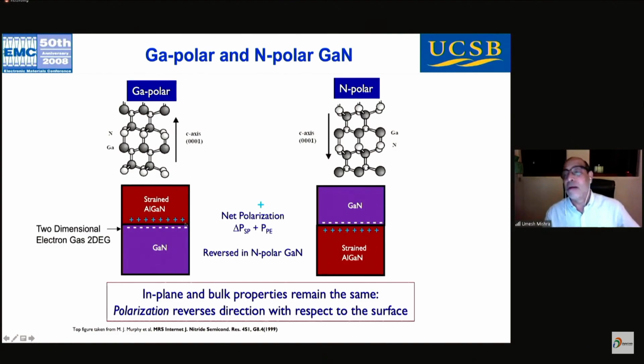When we say gallium nitride, at least folks talking about lateral gallium nitride devices, you basically grow aluminum gallium nitride on gallium nitride. Aluminum gallium nitride is strained on gallium nitride, and this strain induces what we call a two-dimensional electron gas at the heterointerface between AlGaN and GaN. The reason is the difference in polarization, as these materials are polar. What is polarization? Polarization is an inbuilt charge in the material, just by the fact that the chemical bonds in the material are such. So if you put one material with one polarization on a material with another, you end up with a charge equal to the polarization difference. So we don't even use doping. And you end up with a two-dimensional electron gas, which has very high mobility.